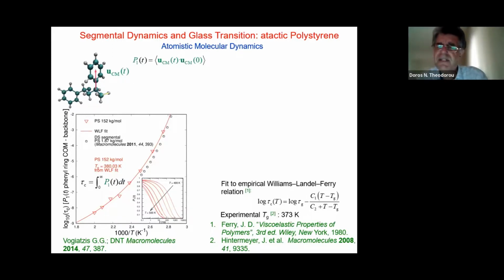If one is interested in something which is very rapidly quenched, molecular dynamics is clearly a representative method. But if one is interested in rates on the order of 1 degree centigrade per minute, for example, which people typically use in calculating Tg, molecular dynamics cannot really inform you about that, unless you do very bold extrapolations with respect to the cooling rate.